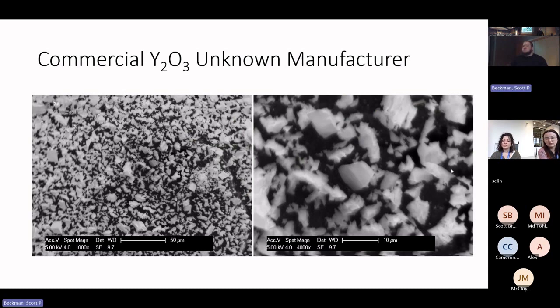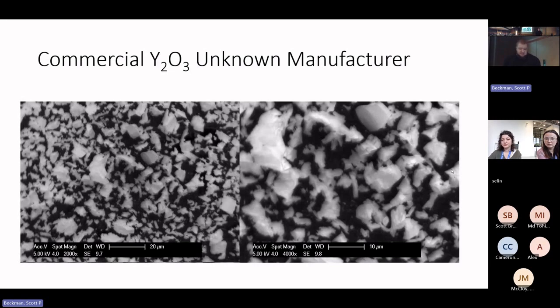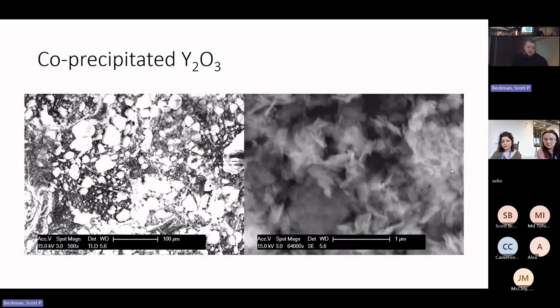We found that we basically had two sets of powders. We had our commercially sourced powder, which I usually call the macro scale powder, which is this somewhat regularly shaped 3 to 5 micron diameter yttrium oxide powder, pure yttrium oxide powder. And then we had our second set of powders that were produced via the co-precipitation method, which you can see here, which are much smaller. They're usually in the order of 100 to 150 nanometers, but you can see that they have a completely different morphology. They almost have this weird platelet snowflake type geometry.